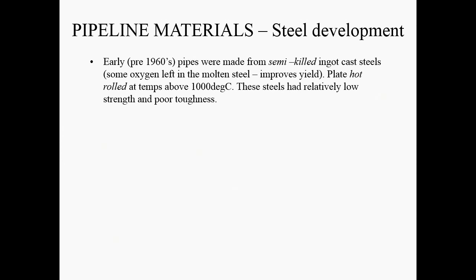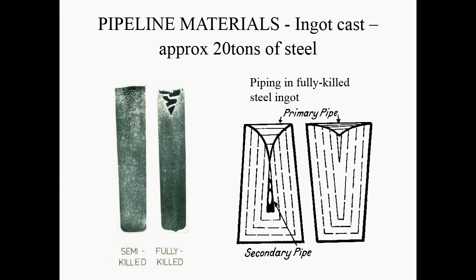And although these steels were better than the other materials that were being used at the time, they still had relatively low strength because of the hot rolling process and relatively poor toughness. So they were easy to fracture because of the oxygen that was left within them. So this is a typical cast ingot. This is a semi-killed steel, and you can see all these little bubbles here of oxygen or air that have been coming out of the steel.